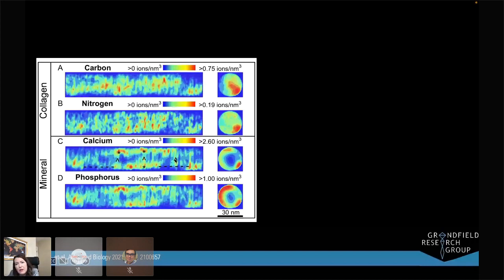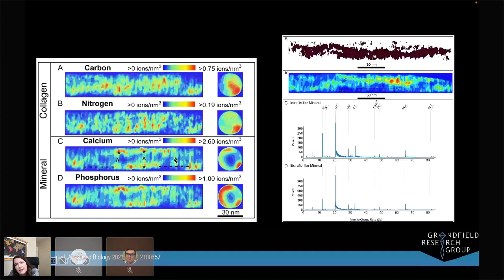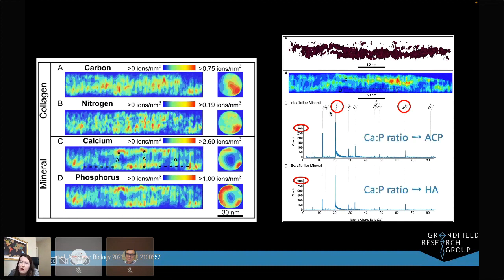When we probe this and look at the spectra, we can extract spectrum from the atom probe for distinct regions, so we can say what's the spectra outside a collagen fibril, and what's the spectra inside. When we compare those, we see that the mineral inside the collagen fibril appears to have a calcium phosphate ratio more similar to amorphous calcium phosphate, and exterior to the fibril, we see a ratio more similar to hydroxyapatite.